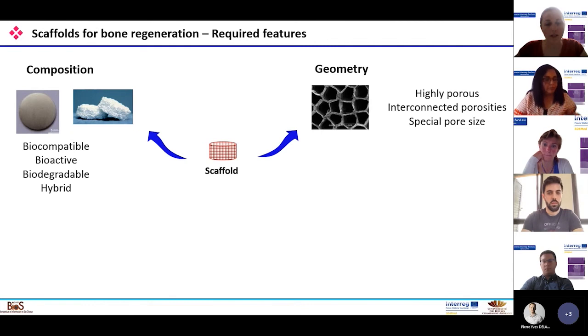Regarding its geometry, the scaffold needs, of course, to fit where it will be implanted, so the shape has to be adaptable. And another crucial parameter for scaffolds is their porosity. Indeed, the scaffold has to allow the different cells to invade it, and it has to be pleasant for the cell. That is why the pore size is determined according to the cells we want to host inside the scaffold. And moreover, once inside the scaffold, the cells need to be fed in order to live. That is why the pores have to be interconnected to allow the diffusion of fluids and nutrients to the cells.